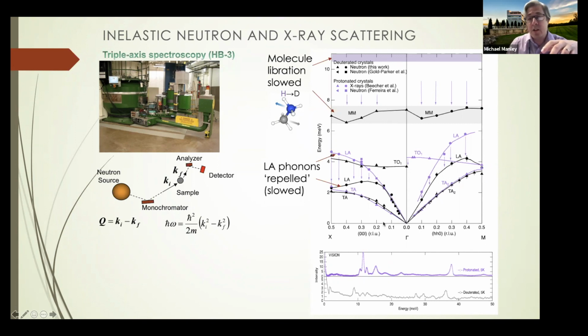And you see it in the other direction. So we call this gamma to X. That means it's propagating through the face of the crystal, and this one, gamma to M, M is on the edge of the crystal, so it's kind of propagating along the edge. And you see an effect there as well, though it's stronger along this direction. So I don't expect you to be familiar with this, so I'm going to try to explain to you why mode repulsion happens in general. It's a really general effect.